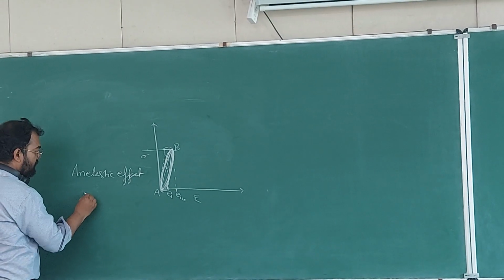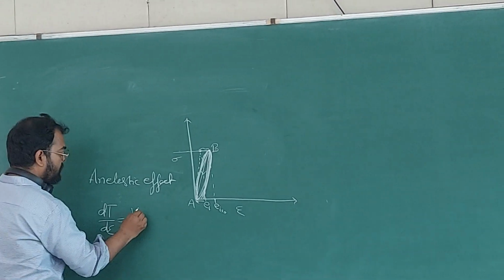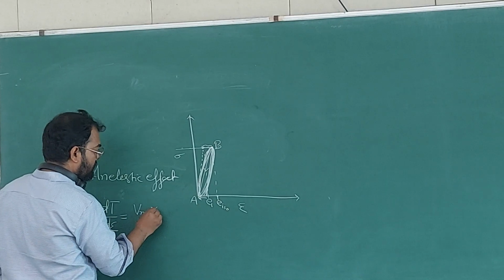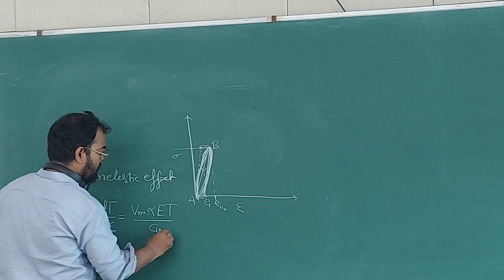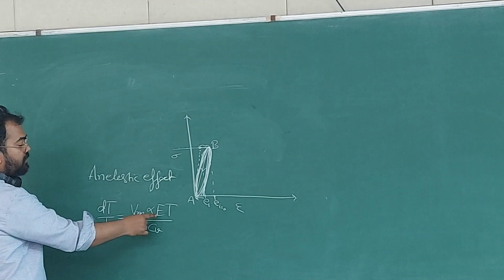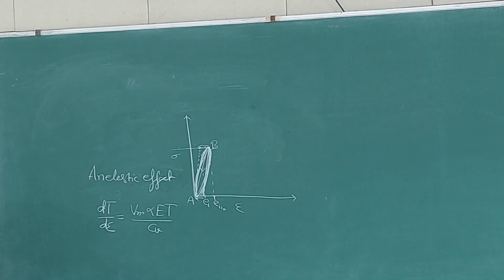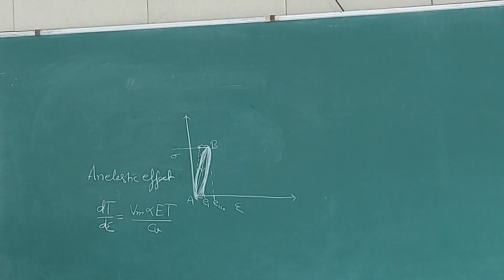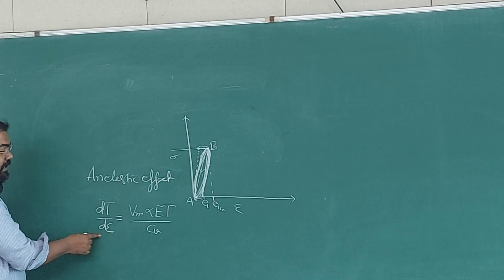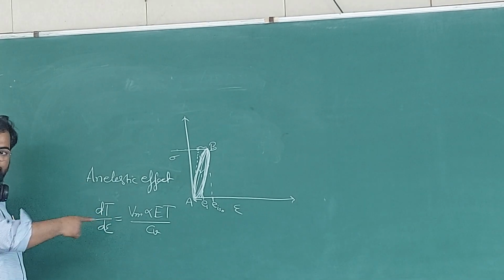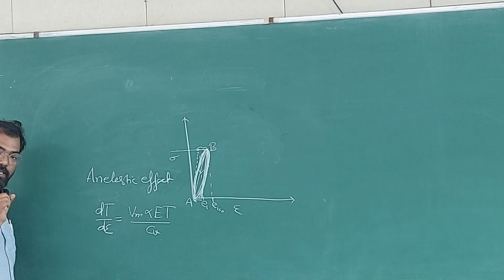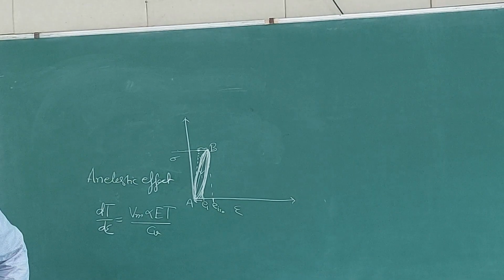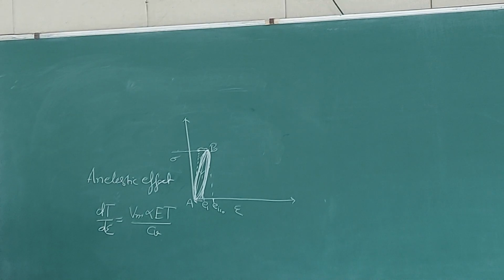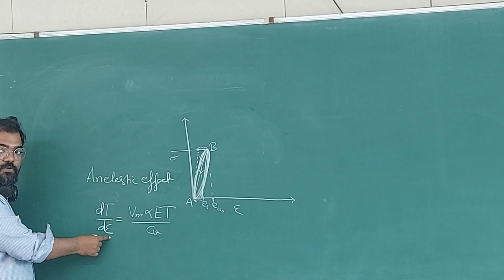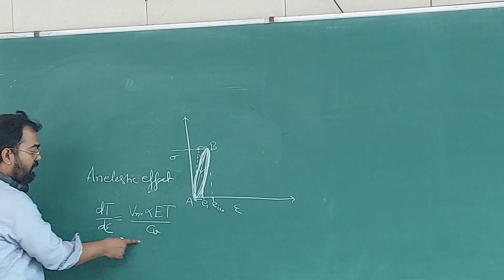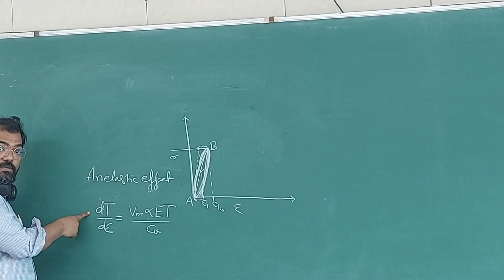And the relation can be written as the rate of change of temperature with respect to strain is the molar volume, thermal coefficient of expansion, elastic modulus, temperature and specific heat. Okay, so any positive increment in this will decrease this term, so that will cause lowering of temperature. So then I mistakenly said that any tensile deformation will cause lowering of temperature, lowering of sample temperature. It will cool the sample temperature. And any compressive, so when this becomes negative, then what will happen? So all these things are positive, okay? So when this becomes negative, that also has to be negative, okay?